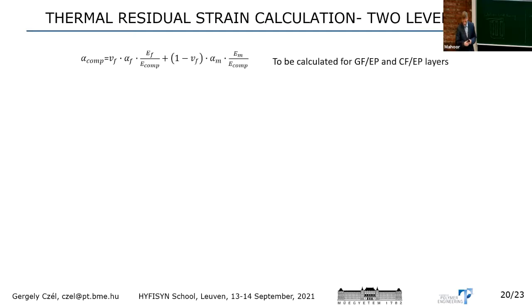And just very quickly, I show a good approach to this. So we can use a multi-level rule of mixture. So first we can calculate the coefficient of thermal expansion of the two components of the hybrid, for the carbon epoxy and then for the glass epoxy. And then we can use the same equations considering the stiffnesses of the constituents.